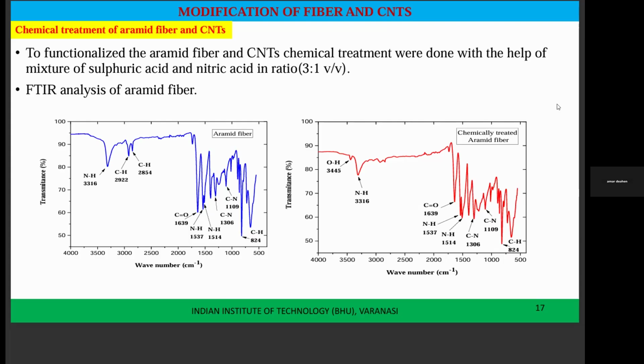And in case the hydroxyl group is already there before coating, that value will be increased for the functionalized one. If it is not there, it will form. So in this particular case, in the left side image, the aramid fiber, there is no hydroxyl group, but in the second image, a hydroxyl group has been formed. It says that it is functionalized, there is proper bonding, and it is oxidized, and you can expect the enhanced properties. Next slide, please.